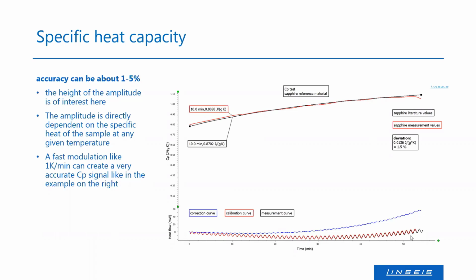So basically both of these materials are sapphire, so they are basically the same. And then I do the evaluation for the CP, and at the upper part of this diagram, you can see in black the literature value for sapphire. And then in blue, we can see the result of another sapphire, and the biggest variation here is 1.5%. So, yep, this looks pretty good here.